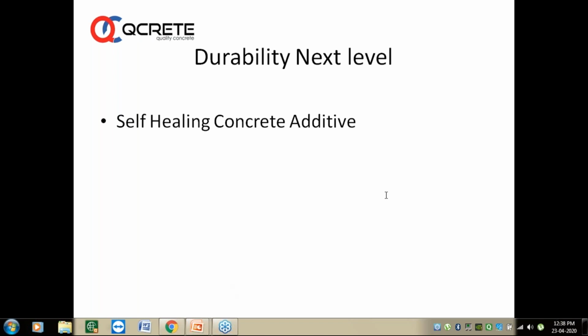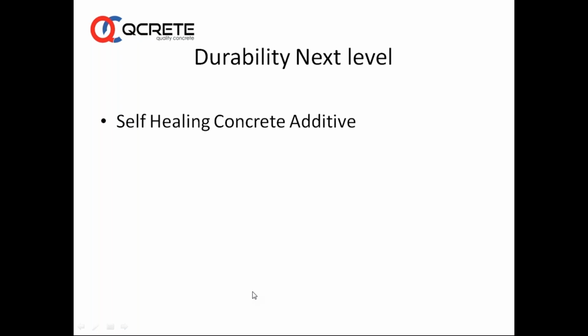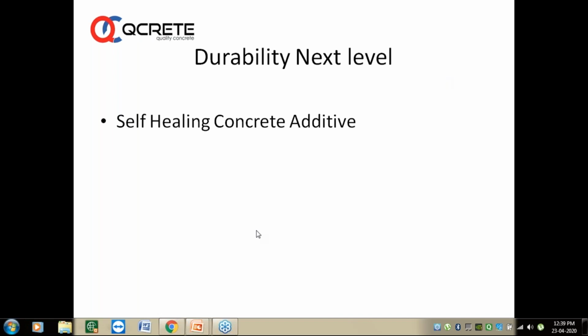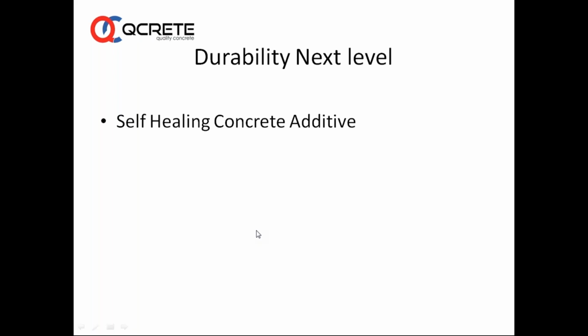They are mixed during production of concrete, and once the concrete sets, if there is any crack in the body of concrete, once the water and oxygen enter through the crack and touch these capsules having bacteria, they open up and react with this oxygen and water to precipitate and generate some products closer to calcium hydroxide or calcium carbonate, which will fill up the cracks. So whenever cracks open up, these bacteria get activated and react and fill up the cracks to make sure that the cracks are sealed very quickly.